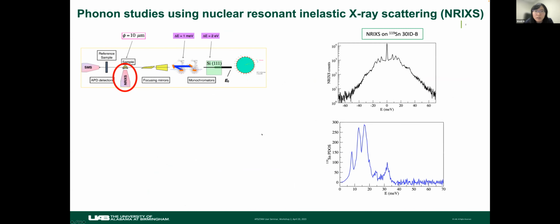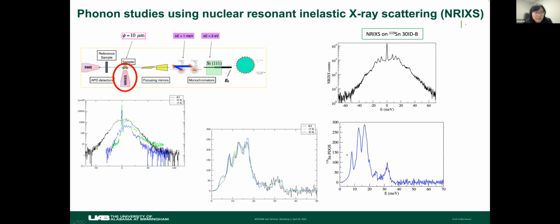Okay, and then we also did tin NRIXS experiments at sector 30-IDB with Michael. We first took a piece of single crystal sample and put it in the beam, and again, this is an enriched sample, so the count rate was really good, and this was done on a very large crystal, and we can get the phonon density of states on the tin side. And then we cooled down to low temperatures. I think in this case, we didn't use a focused beam, so a very large beam. We stacked several crystals on the holder, and we just cooled down and collected data.